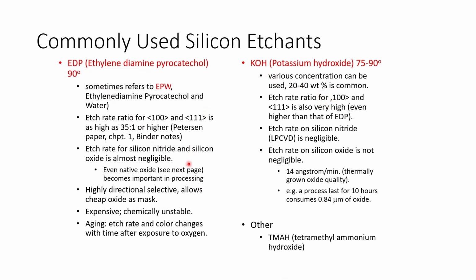It used to be that a lot of people used EDP because the etch rate ratio is very high. But nowadays, people have started to use KOH almost predominantly because EDP is an organic solution that has a very strong smell. So it might be difficult to dispose of environmentally.